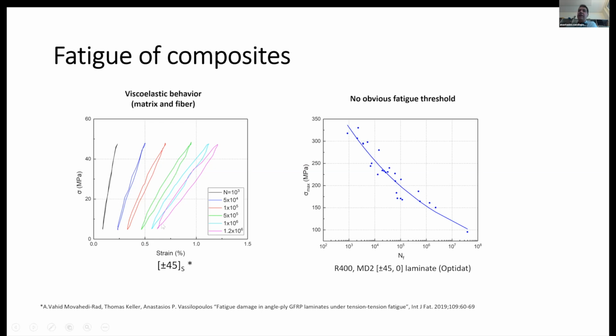And we see these are the hysteresis loops of the material. And we see a drop of the stiffness. So the drop of the slope of this loop shows that the stiffness of the material reduces. And also we see an increase of the area. The area inside the loop is assigned to the dissipated energy. So the more the area is, the more energy we dissipate, which means that we have damage in the material, because the energy dissipated is due mainly to the friction between the material molecules. And when we have damage, it means that we have cracks, and this friction increases. And that's why this area is increasing.